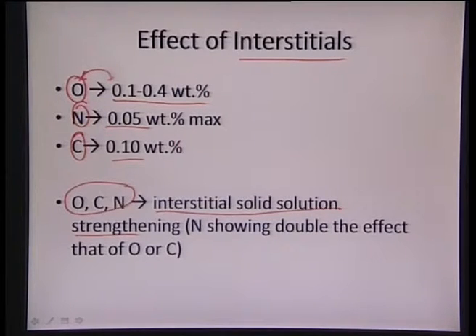So we can see that once the carbon or oxygen or nitrogen are in the interstitial site, they induce solid solution strengthening of the titanium alloy. And it has also been observed by researchers that nitrogen shows approximately double the effect of either oxygen or carbon. So if we have nitrogen sitting in the interstitial, it will provide much more strengthening effect in comparison to that of our oxygen and carbon. But at the same time, we can add a maximum nitrogen of around 0.05 weight%.